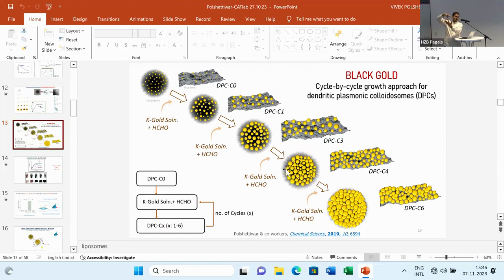So there's a diffusion barrier when you grow the C0 to C1 to C3. And that's why you see this is more realistic cartoon where we saw a heterogeneity in the particle size. We attempted to stop that, but it's just impossible. Because of the way the DFNS is, you will always have the diffusion issues. Like some will get faster and some will get slower in terms of getting these gold atoms. I mean, last question.